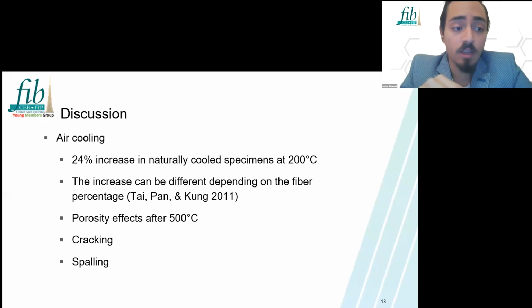It could also be due to the additional hydration of cement or silica fume or silica we added in the study. So this will create additional calcium silicate hydrate, or CSH, binder. And this will, of course, enhance the bond between the aggregates and steel fibers and will in turn give us more resistivity to fire. For regular lightweight concrete, we saw that there was no increase at early stage.